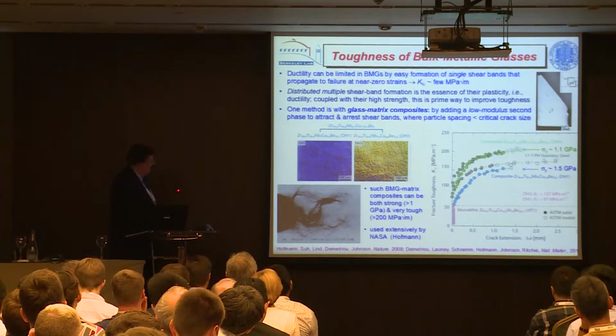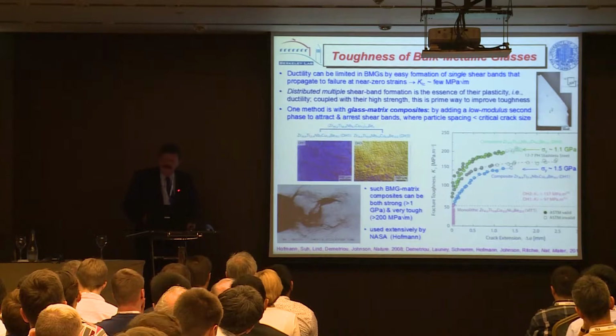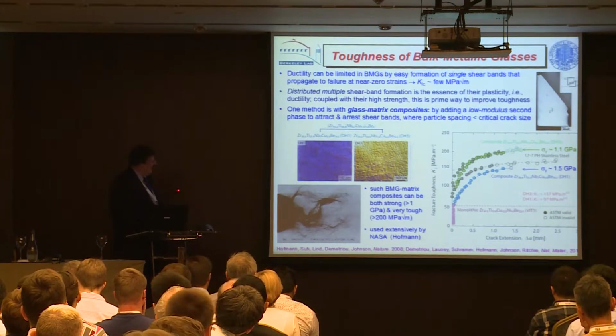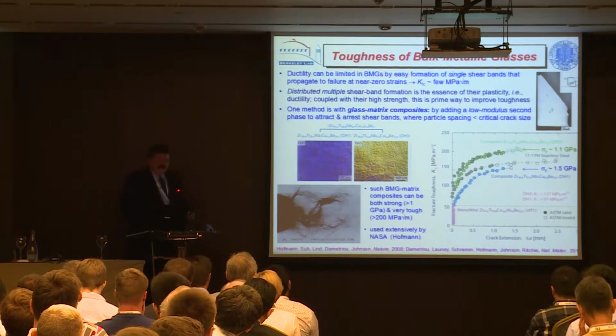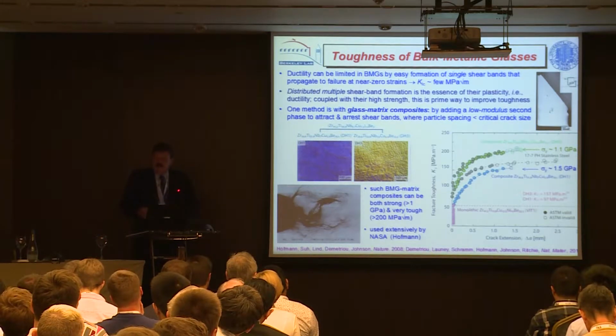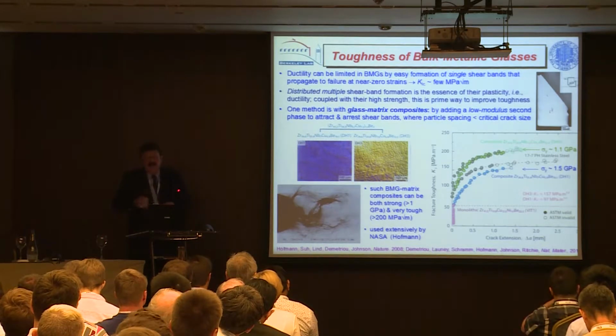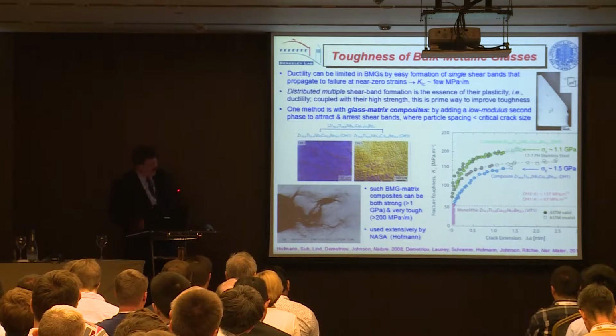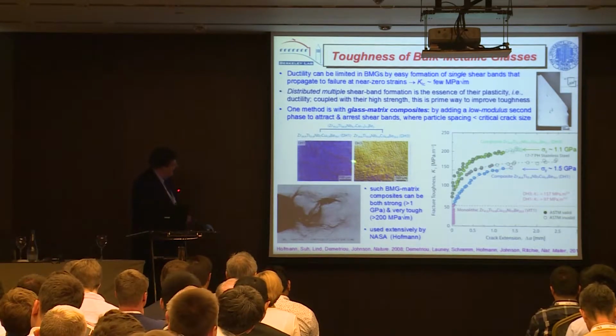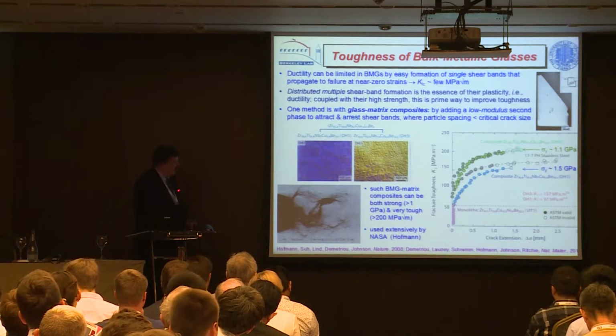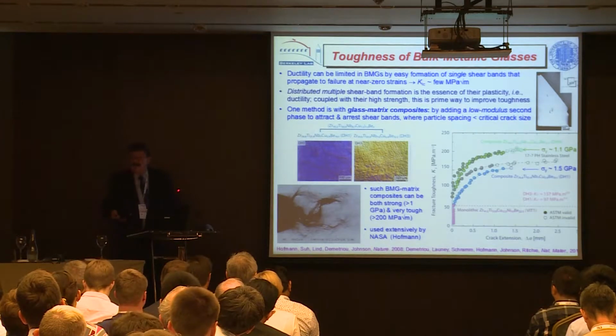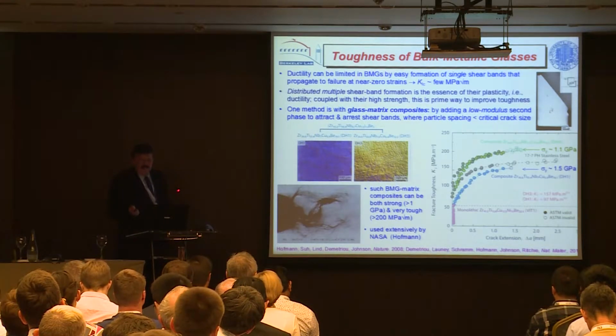I worked with Bill Johnson, who was, of course, one of the pioneers of metallic glasses, and he came up with this idea that if you could block a shear band, then more shear bands would form. So he developed so-called glassy composites. He put a second phase in. It's a dendritic phase.